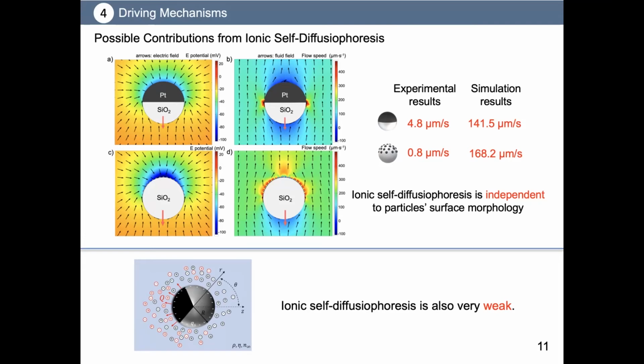So silica-platinum film and silica-platinum nanoparticle would share the same chemical gradient and electric field profiles. According to the simulation results, silica-platinum film and silica-platinum nanoparticle have similar speeds when they are driven by the ionic self-diffusiophoresis. It is reasonable. However, this result is inconsistent with our experimental results. So ionic self-diffusiophoresis is also very weak.